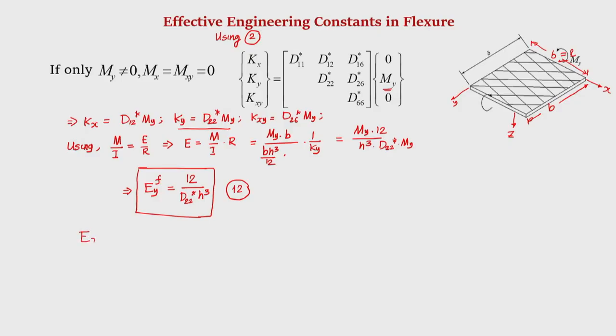However, for a symmetric laminate, we could obtain the expressions for Ex, Ey, okay, Gxy, nu xy, also the shear coupling coefficient, in plane response, as a function of elements of A matrix and H, okay, the thickness of the laminate.